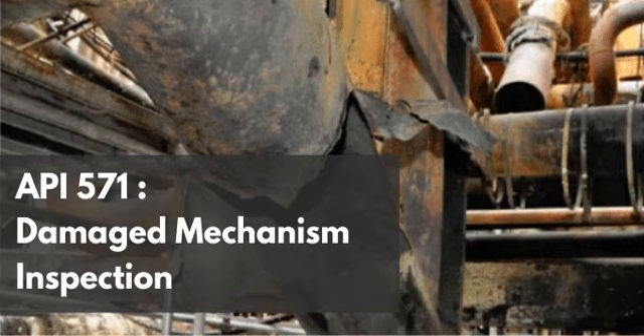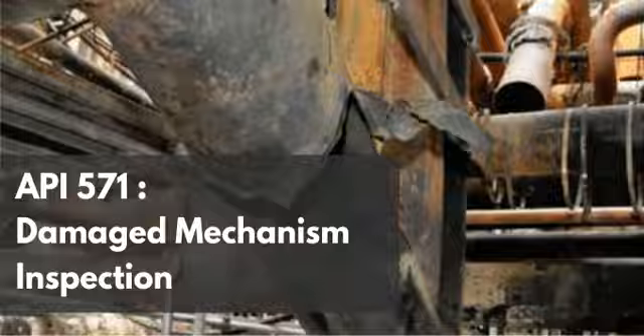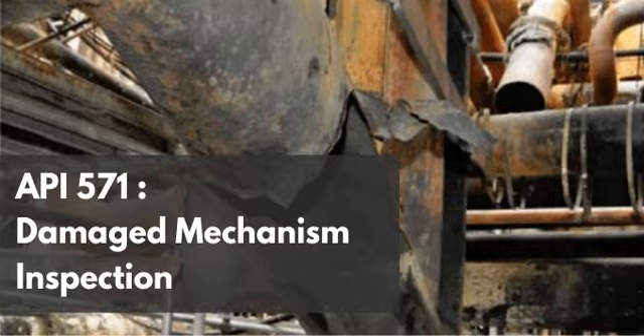Exactly. A flapper wheel avoids this by providing a flexible, compliant, abrasive surface. It removes the brittle scale and polishes the steel without imparting the massive, localized compressive forces required to smear the ductile base metal. And grit blasting and high-pressure water blasting achieve the same goal through erosive action rather than heavy grinding. Right. The text demands surgical cleanliness that preserves the microscopic integrity of the crack mouth.